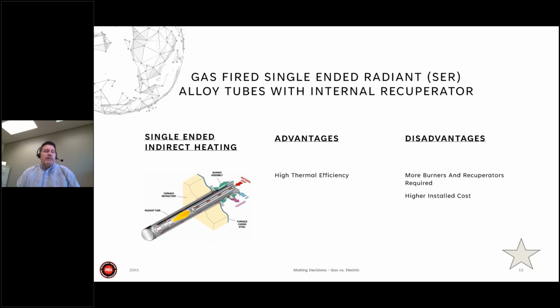This gas-fired radiant tube is actually a single-ended radiant tube, and it has alloy tubes with an internal recuperator. So the burner would send the flame through the center of the burner tube, and along the walls of the radiant tube, the exhaust would exit the burner. This gives higher thermal efficiency with the residence time of the flame. But there's only one leg or one tube, so you need more burners and recuperators to get the same amount of heat input. And so there's a higher installed cost.